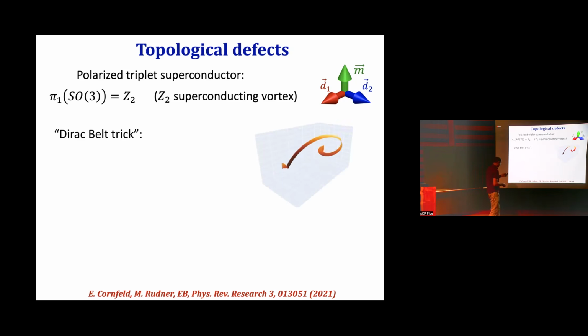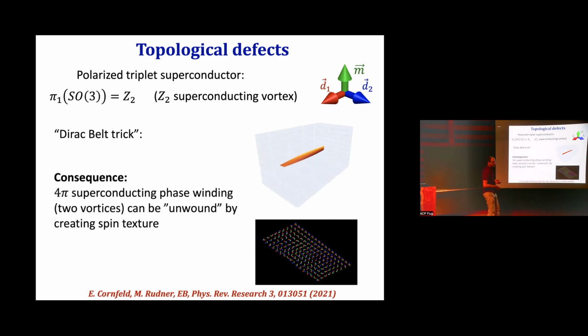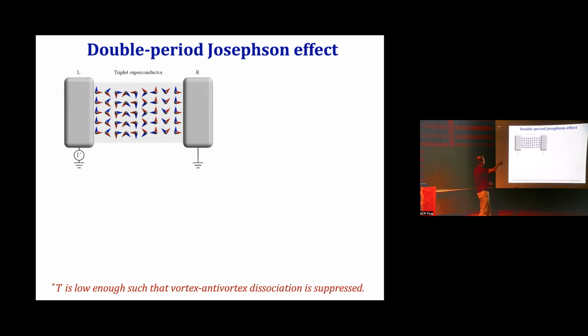So what this means in practice is that in such a superconductor, if the superconducting phase winds twice, by 4 pi, it can actually be unwound without creating any topological defect, by creating a spin texture. That actually has some interesting physical consequences. Asa, who's here, actually stimulated me to think about this. This would lead to an unusual AC Josephson effect.